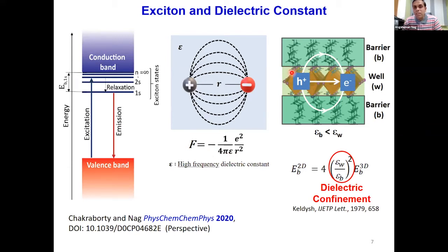Now, when I have this kind of layered perovskite, I have electron and hole residing in the inorganic layer because of the quantum confinement that we discussed in the previous slide. However, the lines of Coulomb forces extend not only in the inorganic layer, but also through the organic layers. So now you have a complex situation where the Coulomb force depends upon the dielectric constant of both the inorganic and organic layer. And in such a situation, to address a somewhat similar situation, Keldysh gave an equation long back.